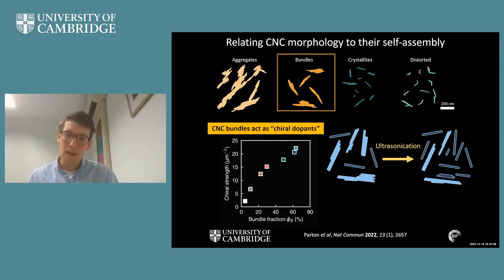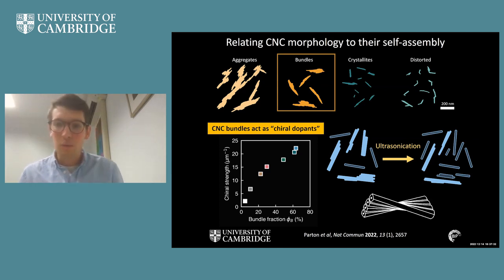And essentially our idea here is that these bundles are acting as these agents which cause the other CNCs to twist. And so the reason that the ultrasonication weakens the twisting interaction in the suspension is essentially that the bundles are being broken apart, they're being blasted into crystallites, and so we're effectively removing the chiral dopants from the suspension. And so in terms of their 3D shape, because I've been showing you a lot of images here, but this has all been 2D. In 3D, we have evidence that the bundles have a morphology a bit like this bow tie or propeller-like shape at the bottom there, where in fact I called them a Kit Kat before, but in 3D, it's more of a propeller-like structure where there's a twist along the direction that they're laterally connected.